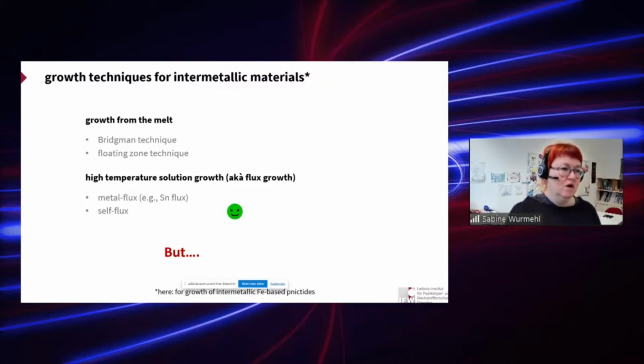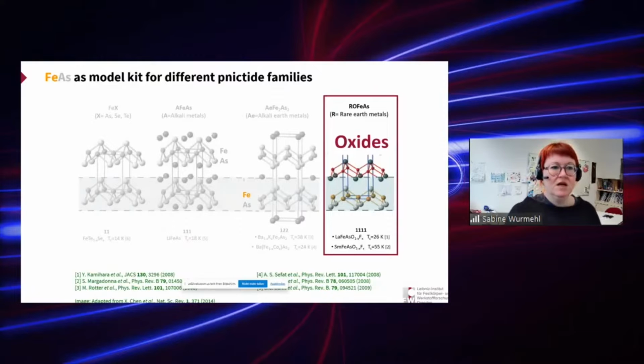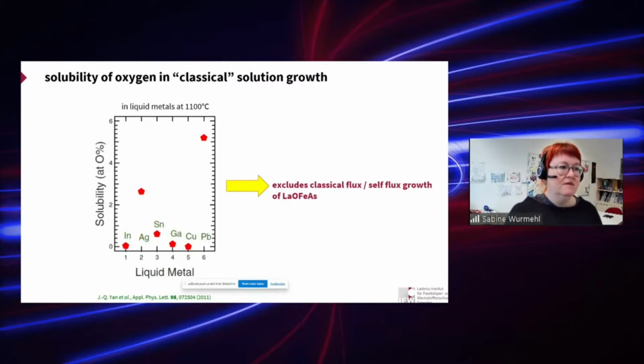This actually led to very nice crystals from the very beginning, because these are very powerful tools for the growth of intermetallic materials. But the oxypnictides are oxides, and the problem is that the solubility of metals is very low in the typical fluxes and self fluxes used for the growth of the 1-2, 1-1-1, and so on. For growth from melt or flux, you need to dissolve both components, the oxide and also the metallic components of these 1111 materials. This is apparently a problem.